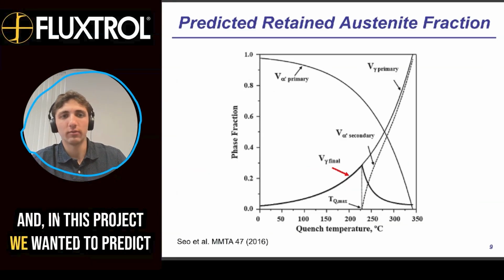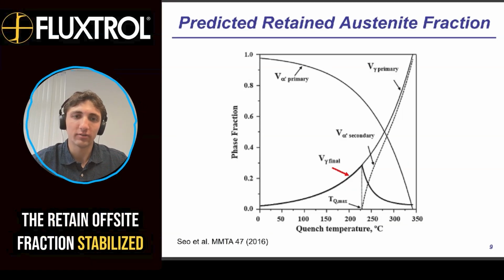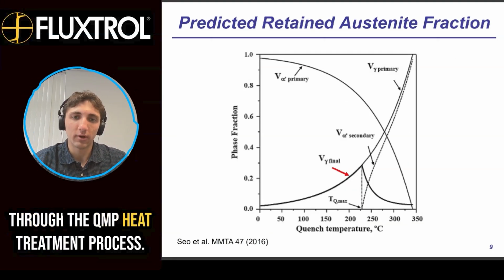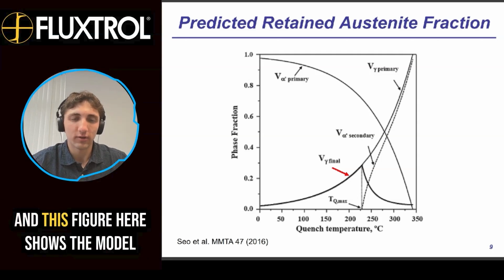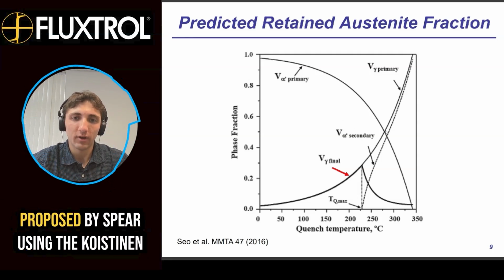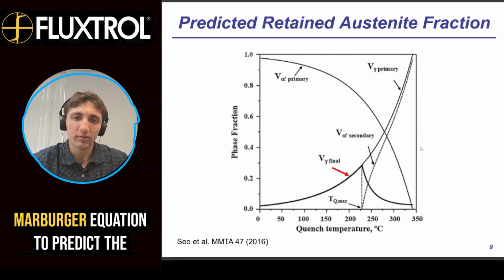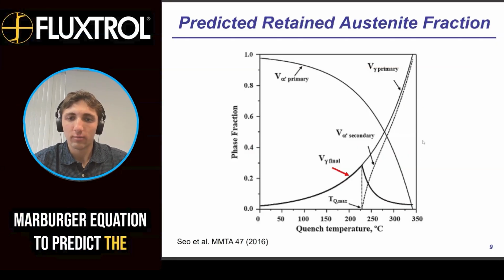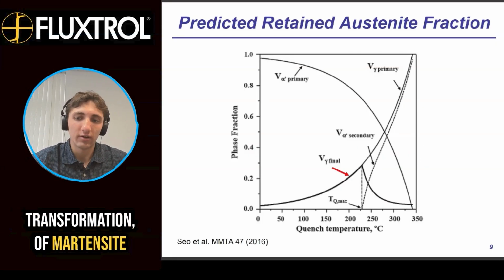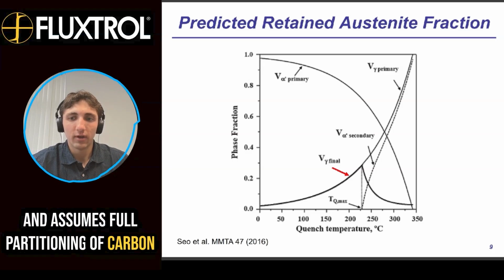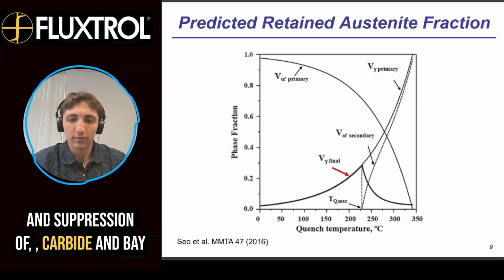And in this project, we wanted to predict the retained austenite fraction stabilized through the QMP heat treatment process. And this figure here shows the model proposed by Speer using the Koistinen-Marburger equation to predict the transformation of martensite, and assumes full partitioning of carbon and suppression of carbide and bainite formation.